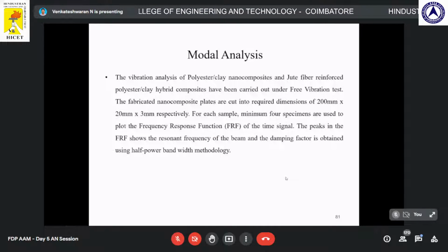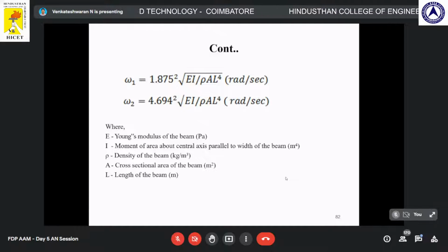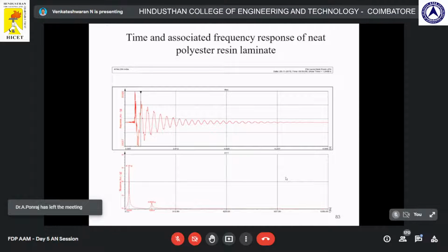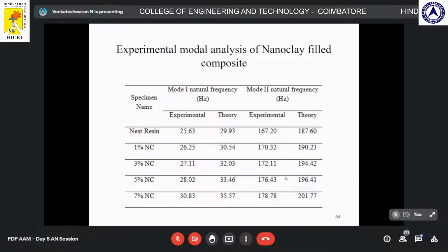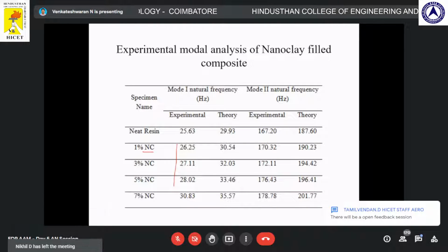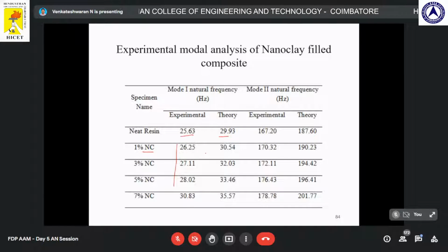And the next, modal analysis or vibration analysis, was carried out with the free vibration test mode, FVT, and we have also compared it with the theoretical way. This is a frequency response curve, and the table shows that with the addition of nano clay, the frequency increases in both mode 1 as well as mode 2. This is the theoretical and this is the experimental one. There is a deviation, and this deviation may be because the hand layup method was followed.